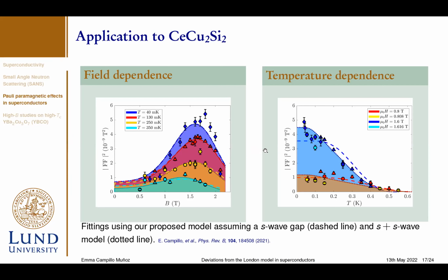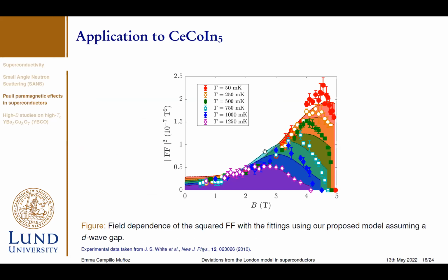Since we don't want to use this model just once, we want to use it in several paramagnetically limited superconductors. We also used it in cerium cobalt indium 5, using the D wave gap that has been previously addressed. And we are really happy to see that, as in the case of cerium copper silicon-2, the model is also able to describe this peak just before arriving at the Bc2 at several temperatures.